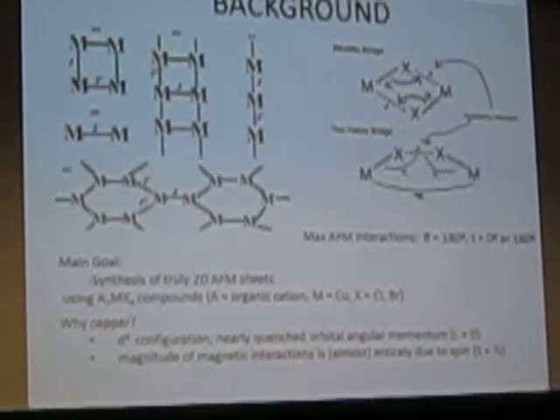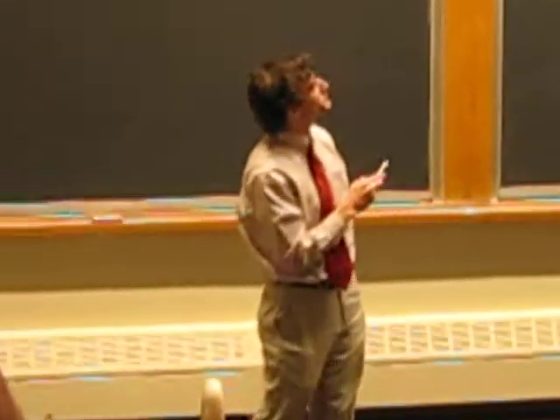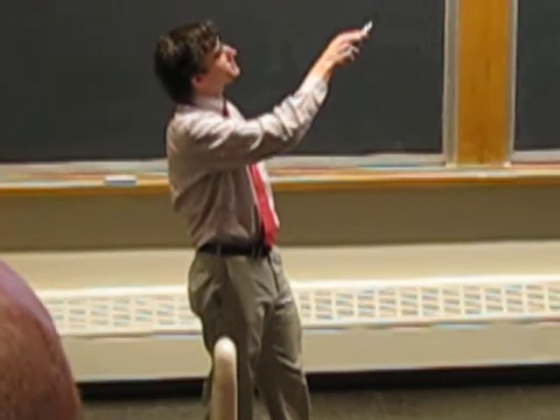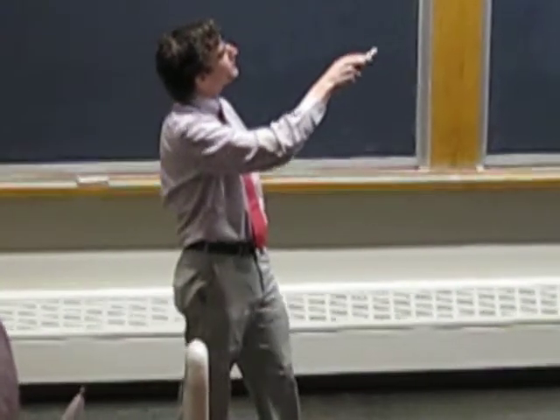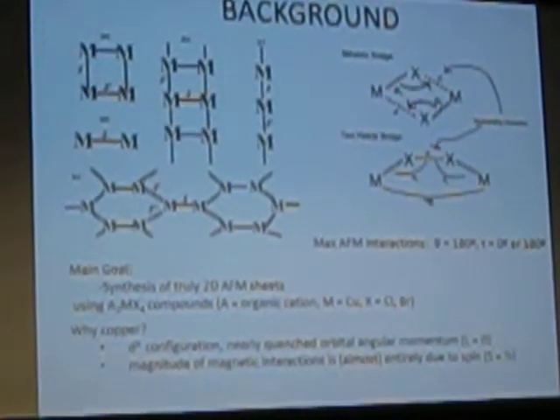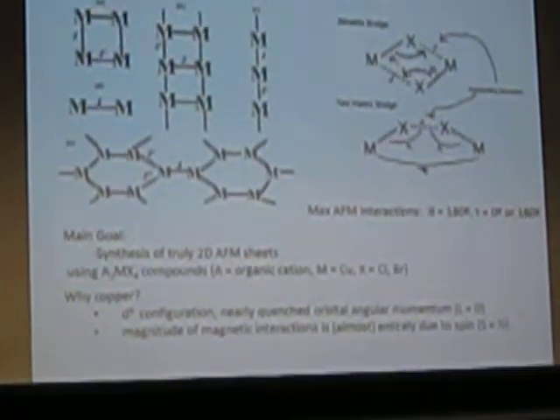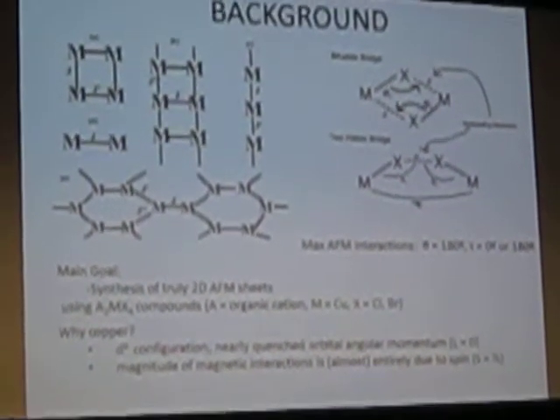So in the monohalide bridge, there's only one halide in between the two magnetic species, and so the only two parameters that we're really looking at is the distance between the magnetic ion and the non-bonding interaction between that and the halide, and the angle that it creates between all three atoms. In the two-halide bridge, there's an additional parameter, the dihedral angle, that's created by the lines that you can draw through the metal halide bonds on either side.